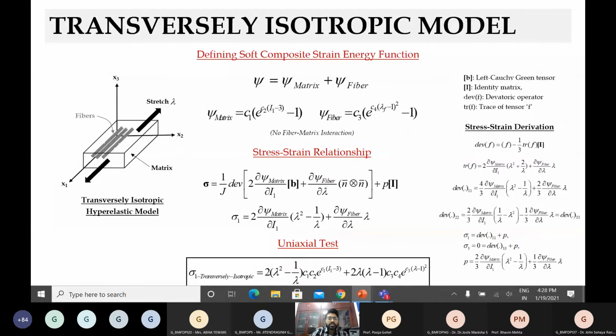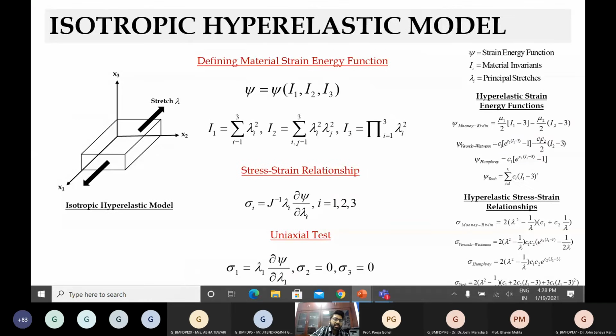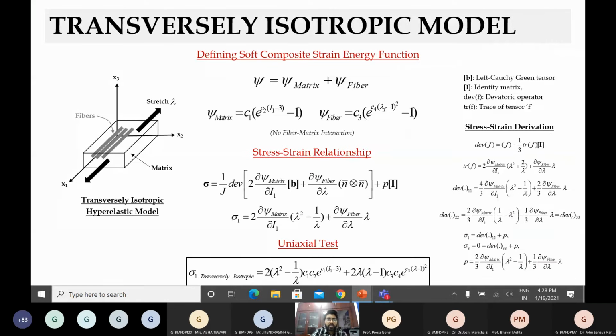OK. So the next step is a much more complex model, which is called a transversely isotropic model. I'll not get into too much of details. So in the earlier model, we were looking at just a single blob of material, no fibers, isotropic. Here we are looking at fibers. So we are looking at fibers and matrix contribution, but there is something which is not there, which is there is no fiber matrix interaction. So the model does not understand what really happens between the fiber and the matrix when there is a pull, because both cannot get pulled in the similar fashion, like they have different stiffnesses and material properties. If you pull one material more, the other will get pulled less. So that kind of interaction is not really captured in this model.